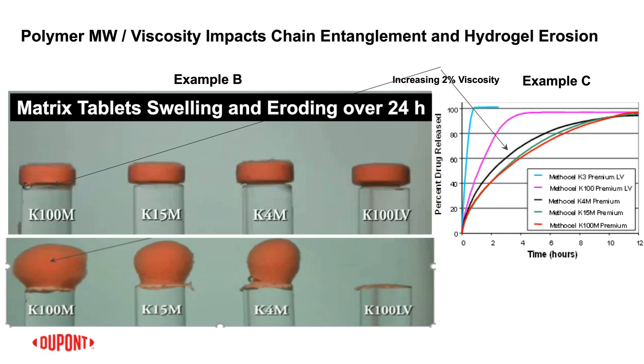But you get the drift, right? You see here with increasing viscosity grade or increasing molecular weight grade on the right-hand side, you go from essentially an immediate release type of profile with the light blue to an intermediate type of modified release profile with the magenta or the pink. And then, as you go higher and higher with your molecular weight grade of HPMC, you slow that release down more and more.